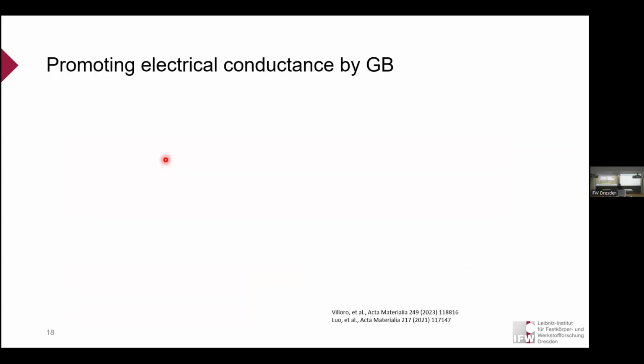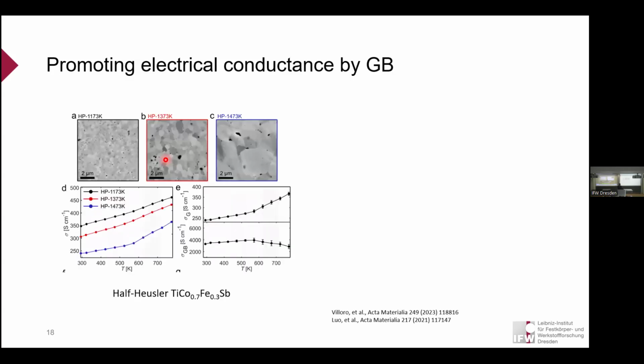Then that's part of the story, but there's another half of the story. So usually we would think that grain boundaries are charge carrier scattering centers. And the smaller the grain size, the stronger the scattering for charge carriers and the higher the resistance. But we also found that in some special materials, the trend is opposite. For example, this is a half-Heusler material, titanium, cobalt, antimony. And we could replace, let's say, 30% of the cobalt site with iron, and we can change the sintering temperature in the sintering process, and we can increase the temperature and increase the grain size. But surprisingly, what people have found is that when you have the largest grain size, the conductivity turns out to be the smallest, which is quite counterintuitive.